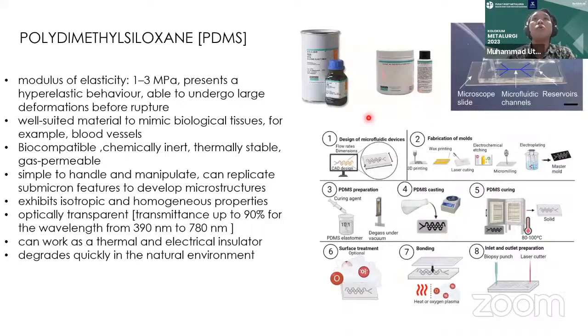And the way we use these chemicals, or PDMS, is we mix the PDMS elastomer and the curing agent, usually at a 10:1 ratio. So they usually come like this. We have this elastomer, and this is the curing resin. So we mix them together at a 10:1 ratio, and then we degas, or we take out the air from the mixture, and then we pour the PDMS on top of the silicon wafer that already has micro features from the soft photolithography process.